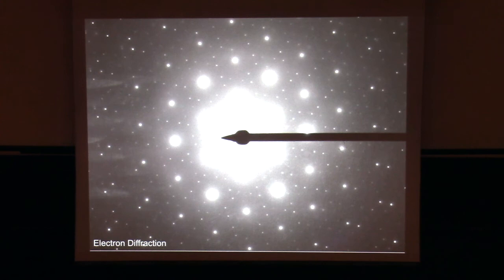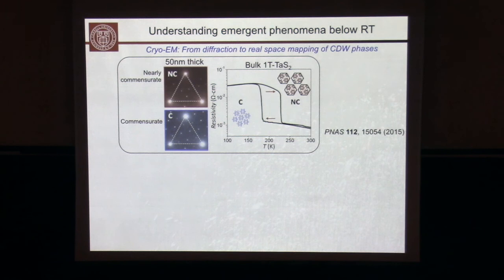So why are we interested in this? The reason why you're interested in charge density waves is, one, they couple very strongly to electronic properties. For superconductors, for example, it's been shown that charge density wave order competes with superconductivity. So understanding that would be certainly of interest. And there's lots of effort in doing so. Just as an example of how charge density waves correlate with electronic properties, this is actually bulk 1T tantalum disulfide, a thick flake. As it goes through a nearly commensurate to a commensurate charge density wave state, you see the jump in resistivity.